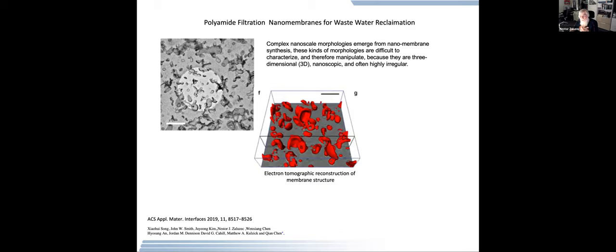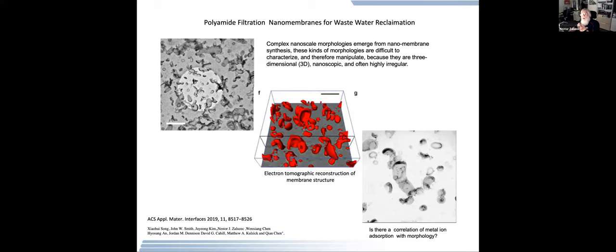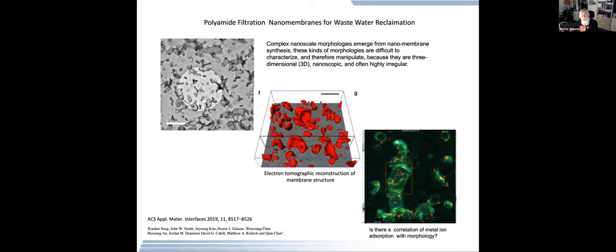But more importantly, what we're interested in is the use of this membrane, and the use of this membrane is in filtration. In filtration, when we look at it, we see dense bodies. And the question we want to know is, what are these dense bodies? These are not crystalline, so you can't do simple electron diffraction to figure out what they are. What we want to do is elemental spectroscopy to find out what they are. So we can do the tomography for the shape, and we can do the spectroscopy to find out what elements are present. And is there a correlation of the metal ion adsorption with site-specific geometries? We can actually begin to see that now.